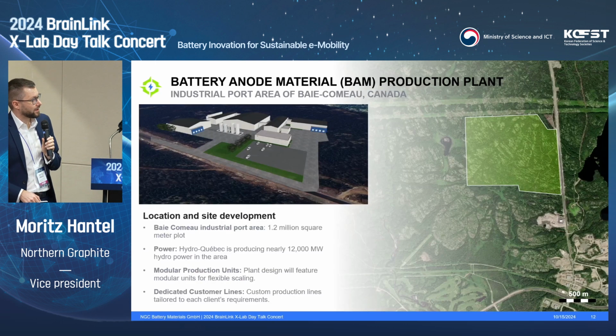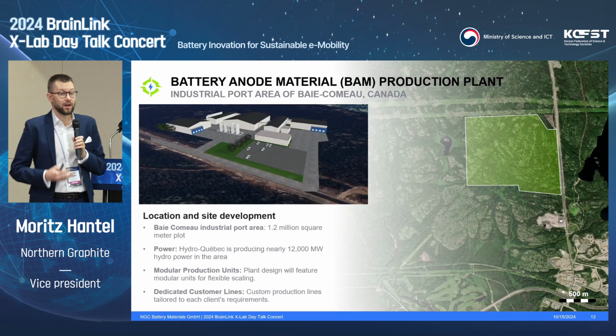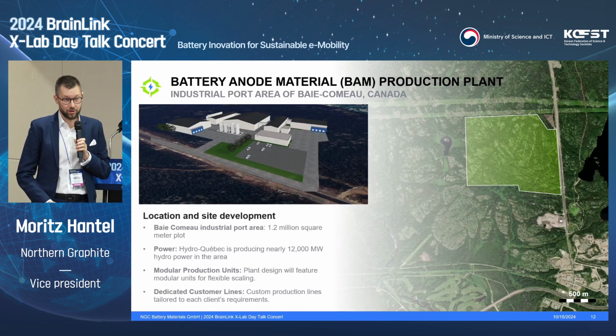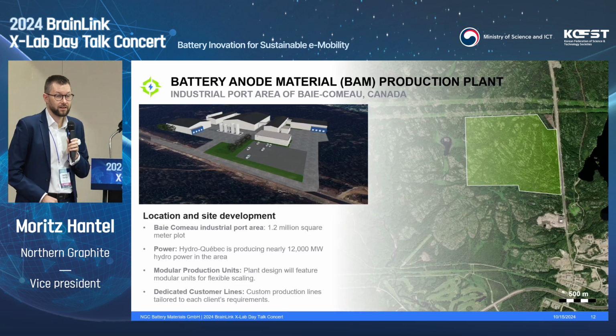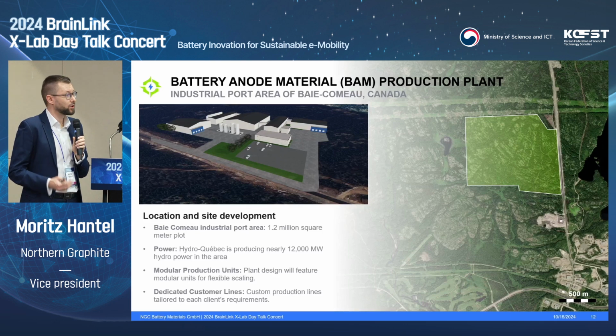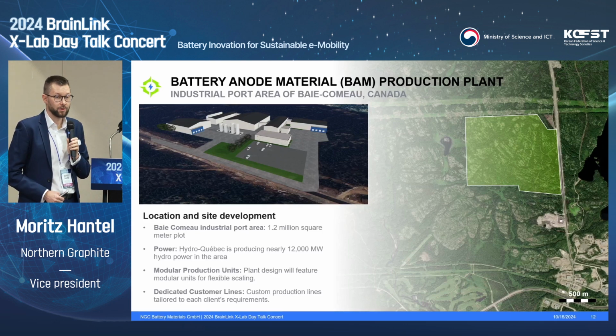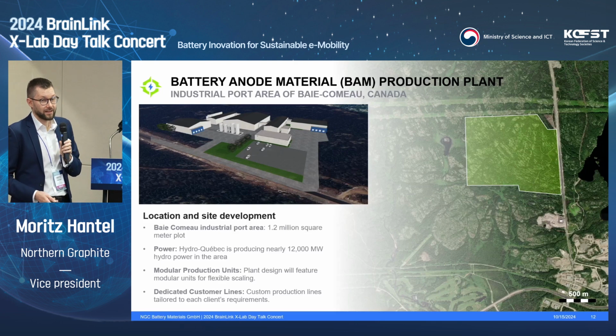A little look at Baie-Comeau, and that's the reason why Canada: processing requires energy. And one big advantage of Canada is the hydropower in the area, meaning we can run the processing 100% with renewable energies, meaning in the end it's a rather CO2 neutral or low CO2 material compared to, for example, synthetic graphite, which typically requires a lot of energy and also byproducts from the steel or petroleum industry.